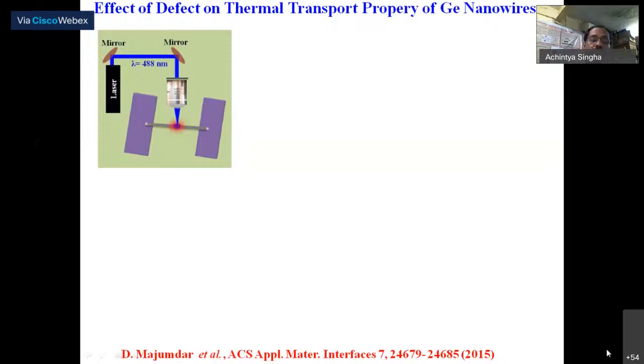Now how much the temperature will increase in the middle of the nanowire depends on the thermal conductivity, the thermal property of the material, here the thermal property of this nanowire. So from the local heating, which we can measure from the Raman spectrum or phonon frequency, you get information about the thermal conductivity of the material. So this is a very simple experiment, but you can get the thermal conductivity of the material from a very simple measurement. So now go next.